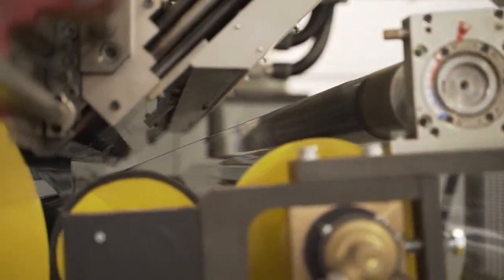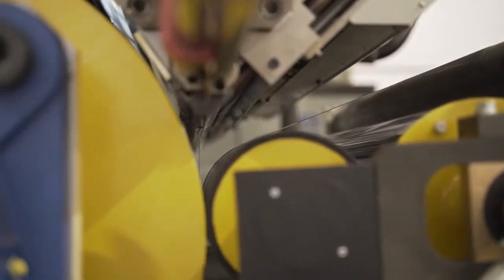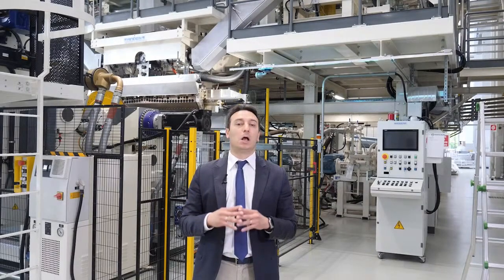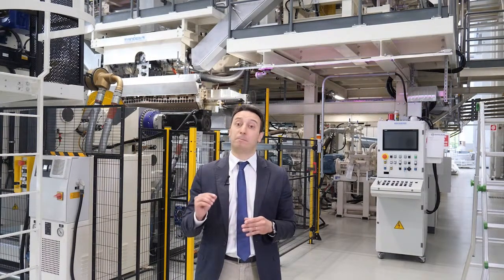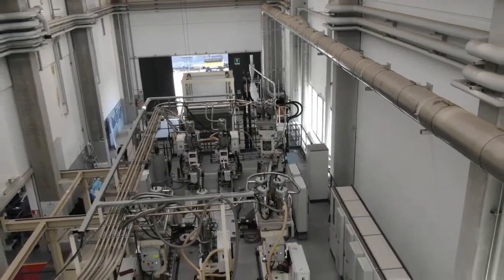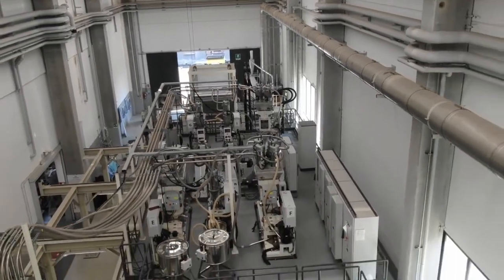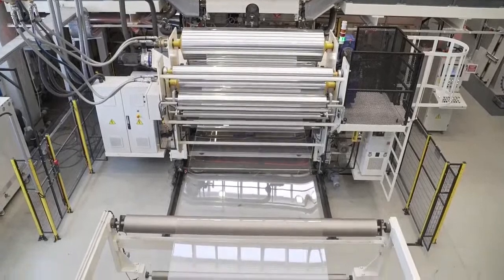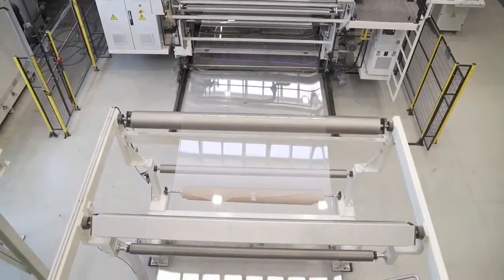The adhesion to the substrate is definitely more performant and steady compared to standard lamination solutions. The aesthetical properties such as transparency and brilliancy are indisputably better compared to other technologies. All these features are highly appreciated, above all when processing functional and barrier resins. About operations, the Bandera extrusion coating island can be supplied as a retrofit for existing sheet extrusion lines, or just like roll-to-roll configuration, using reels produced by standard extrusion lines.